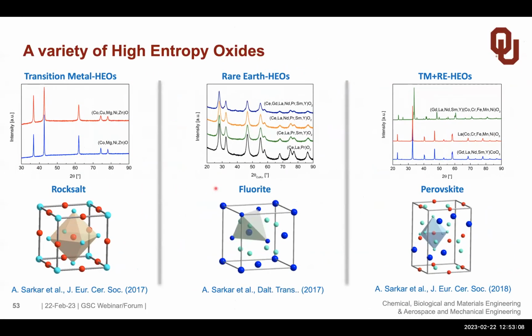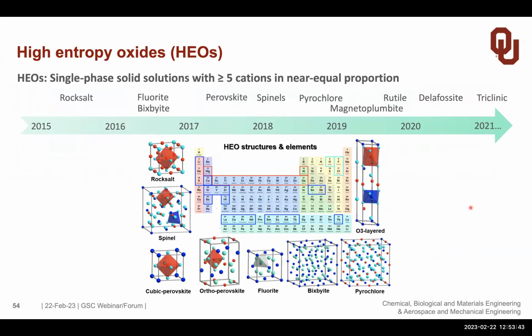There's a whole variety of different other high entropy oxides. So this is the one I just showed you. We also prepared rare earth high entropy oxide, which have a fluorite structure. We prepared perovskite structure, even up to 10 different cations, which you can see over here. We have 2 sublattices. On one, we have the rare earth, on the other one, the transition metals. And so we have a very complex single phase structure, which has a random distribution of the elements.